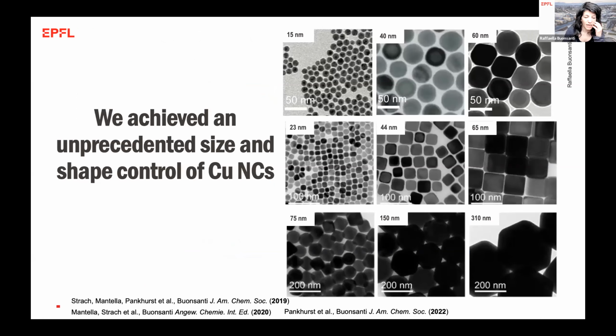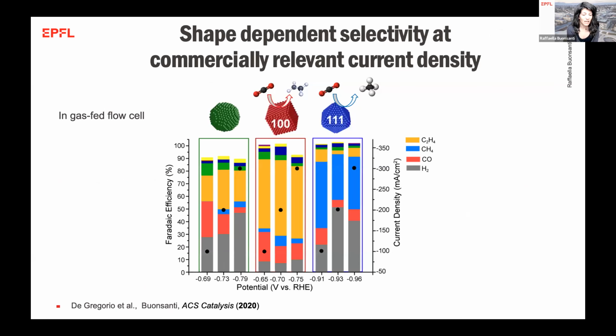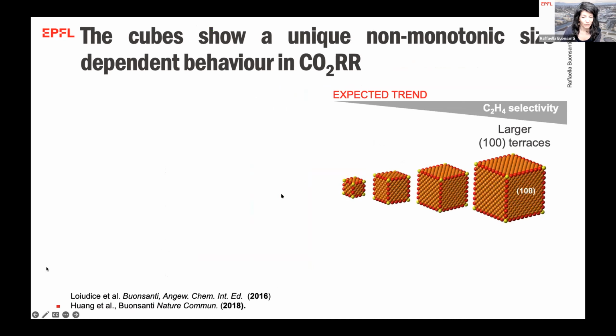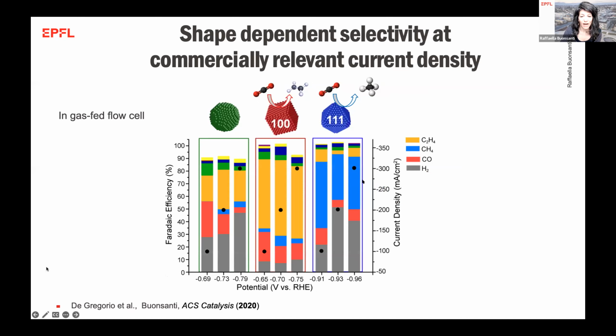And thanks to this measurement, we could identify some of the chemistry involved. And thanks to this, we have been able in the group to synthesize quite a library of copper nanocrystals. Here I'm showcasing simple copper spheres where we change the sizes, cubes where we change the sizes, and octahedra where we change the sizes. With these well-controlled copper nanocrystals, we could measure the Faradaic efficiency, which indicates the number of electrons converted into product versus the applied potential to the device. And we could demonstrate that the cubes, exposing mostly 100 facets, are mostly selective for ethylene, and that the octahedra are mostly selective for methane, which are results consistent with the single crystals, and that the spheres exposing different facets on their surface are actually not selective for any specific product.